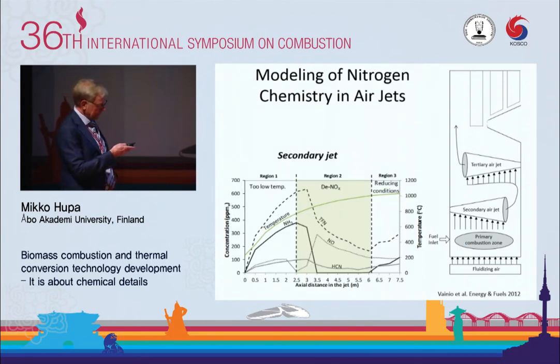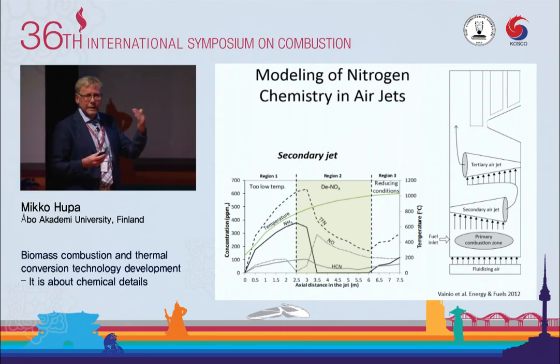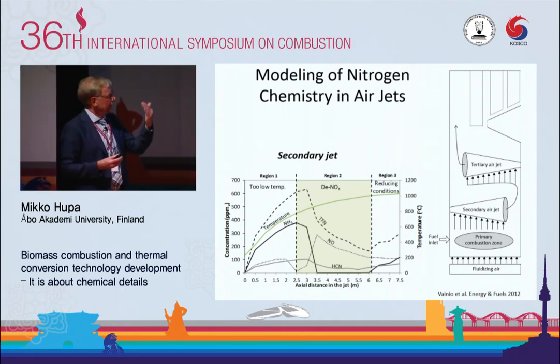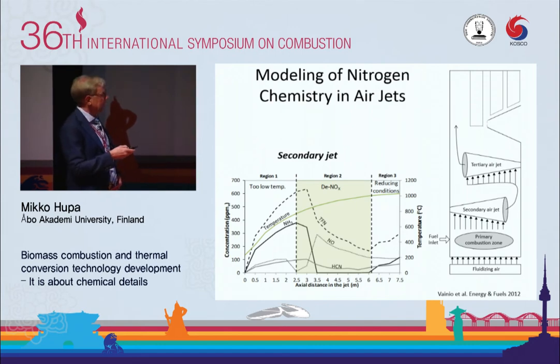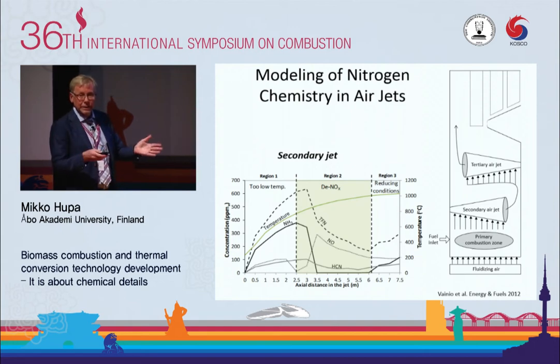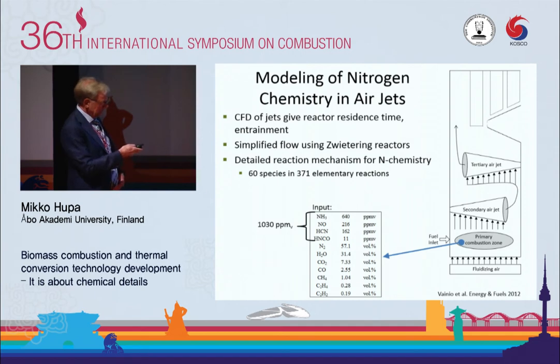And here is the result of that calculation. This, of course, assumes that we have a very efficient mixing radially, which is not the case, but that was the assumption here. Let's look at the results. This is the complete jet. This is 7.5 meters. It's a very long jet. And early, it's almost pure air, of course, and the temperature is low. But the temperature keeps increasing when more and more hot gas is mixed in. Yeah, I forgot to explain that we used as a feeding material the measured primary combustion zone composition.